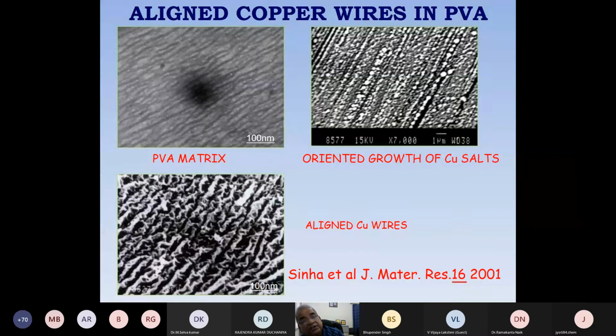And then we could in situ reduce this copper salt into copper metal. So in a single step process, a single aqueous process, we developed aligned copper wires on a PVA substrate. This was one of our very first experiments where we could mimic the biomineralization process using a synthetic polymer for an engineering material.